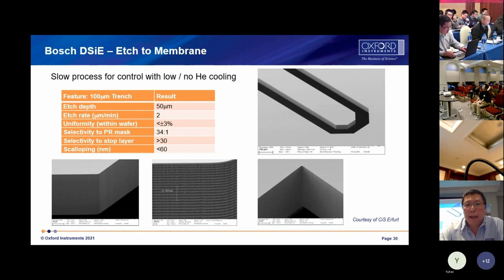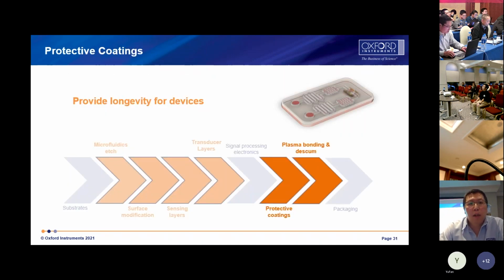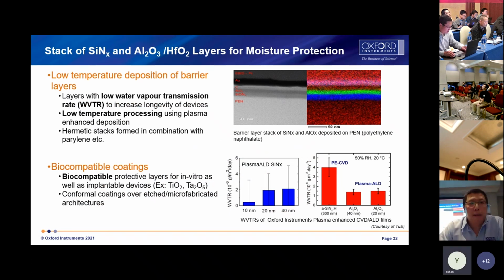The SEM shows the etched cantilever structure. Protective coating provides longevity for devices. A stack of silicon nitride and aluminum oxide, hafnium oxide, which is a high-k material, forms layers for moisture protection. So layers with a low water vapor transmission rate increase longevity of devices. Low temperature processing using plasma enhanced deposition. Biocompatible coating protects your device, so the layer is for in vitro as well as implantable devices.